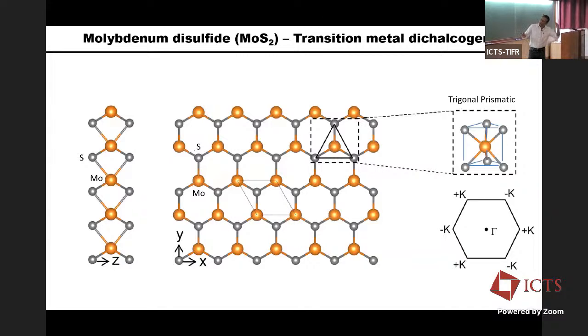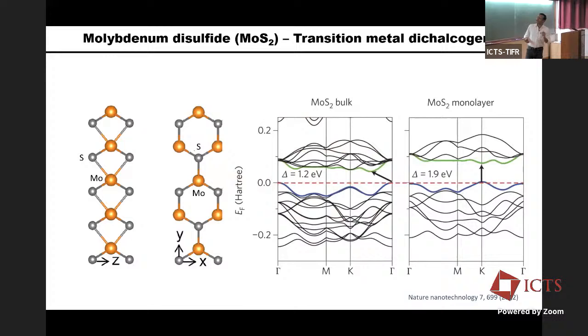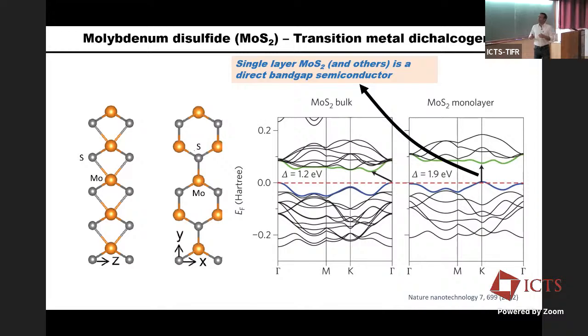In terms of structure, if you look at from the top of it, it is a beautiful hexagonal crystal. And this is molybdenum, this is sulfur. And then the Brillouin zone is also very similar, which is like a K and K prime have something like a hexagonal structure. However, there's a key difference between the molybdenum disulfide and graphene is that this guy has a band gap. See, graphene doesn't have a band gap, but this one has a band gap of about 1.9 electron volt, which leads to a single layer semiconductor that we never had before.